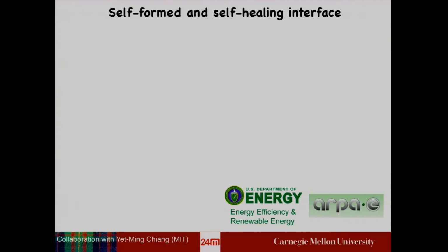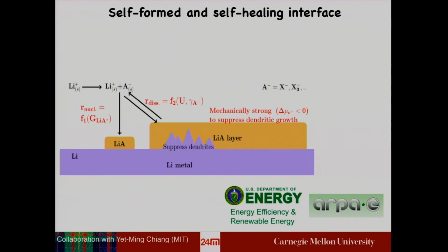And so the question that we are asking is, how can we enable a lithium metal anode and do that in a way where it is scalable and integratable in today's lithium ion manufacturing. The approach that we have taken, and one that's now being funded by DOE through the EERE program and ARPA-E, is to essentially rethink the way lithium metal is enabled. And the approach is to self-form, and the way we will self-form is to add strategically certain components in the liquid electrolyte that is used, and self-form a thin film that is coating the lithium metal, and the coating will have certain properties that can block dendritic growth.